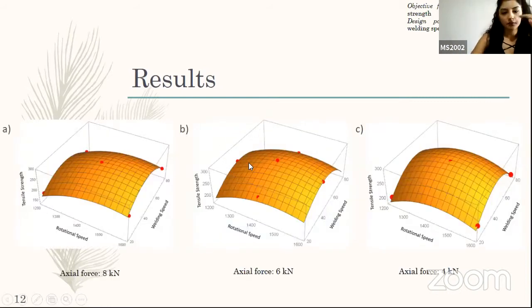And the 3D graphs: these 3D graphs of tensile strength results for the proposed model and those observed experimentally are given here. It is seen that the proposed model fits well with the experimental results. Red dots represent the experimental data, and the yellow area represents the proposed model. We keep the axial force at 8 kilonewton for A, 6 kilonewton for B, and 4 kilonewton for C.